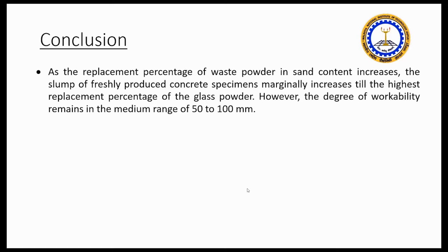So this is the conclusion: as the replacement percentage of waste glass powder in sand content increases, the slump of freshly produced concrete specimens marginally increases till the highest replacement percentage of the glass powder. However, the degree of workability remains in the medium range, between 50 to 100 mm, so there is no problem for that.